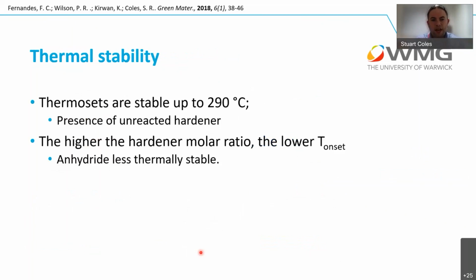The first thing we found when we looked at some of these composites was that the thermal stability was pretty good. They were stable up to 290 degrees C, and then when they were starting to go, they were becoming less stable because of any unreacted hardener. So if the hardener wasn't completely reacting, then that was providing a little bit of thermal decomposition, which is again entirely what you would expect. So the higher the hardener molar ratio, the lower the T onset of degradation was, and typically the anhydrides were thermally less stable than the amines.